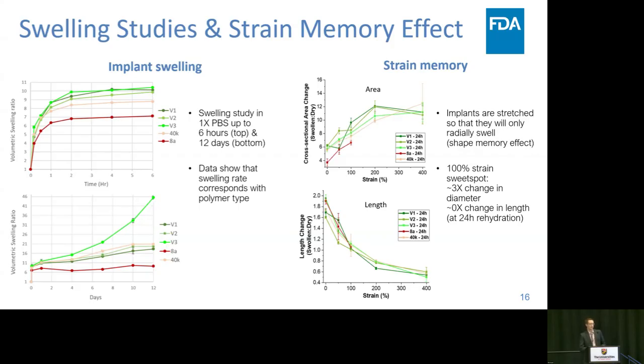And then there's a strain memory effect where if you process these in a certain way by displacing them along a preferred axis, when you do the swelling later on, basically it won't swell very much in that dimension. And you can leverage this to make an insert that will swell in a preferred direction, like we talked about with the radial swelling in the product, so that it accomplishes its therapeutic function in the canaliculus. And by doing this kind of testing, you can figure out a sweet spot on how much change you want in the length and the diameter.